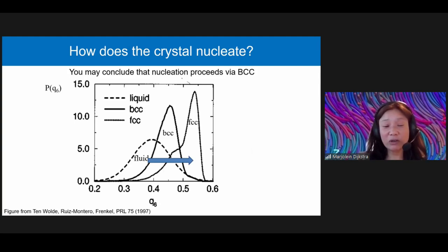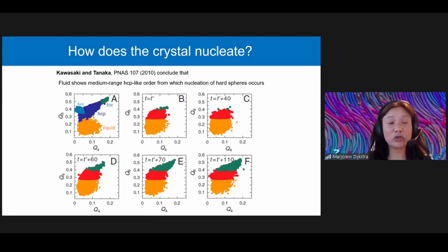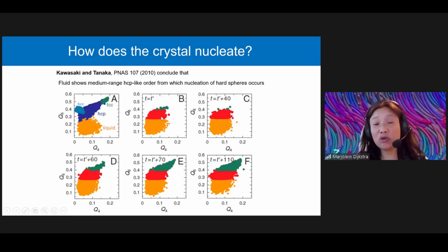If you just use this very simple projection here, one can try to be smart and use both the q6 and the q4 value and make a scatter plot of the typical liquid configuration, hexagonal close-packed configuration, the FCC and the BCC configuration. And if you then plot on top of that a simulation trajectory at different times, as shown here, one may conclude that the fluid already shows HCP-like order and that the nucleation of hard spheres always proceeds via the HCP phase.